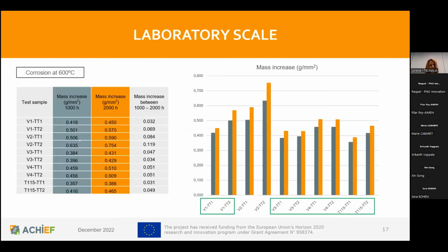Let's see what happens with the corrosion properties of the samples. Here, first of all, we need to take into account that the reference steel we are basing on, which is T115, is really good at corrosion. Okay, so when we change its composition, creating V1, V2, V3, and V4, we do it with the aim of increasing creep resistance. So if we manage to increase creep resistance while preserving the corrosion resistance of the reference steel, that would be a very, very good result.